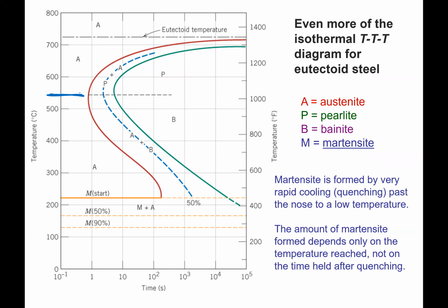And now as we lower the temperature even further, instead of this transformation occurring even more quickly, it actually starts to take a longer time again, and the curve starts shifting back this way. Now this is the case where the diffusion is becoming slow, and it's limiting our ability to transform. And in this particular case as well, when we start limiting the diffusion that way, the system changes from a layered structure to a new one that is more needle-like. And so this needle-like structure is referred to as Bainite to distinguish it from the layered Pearlite structures.